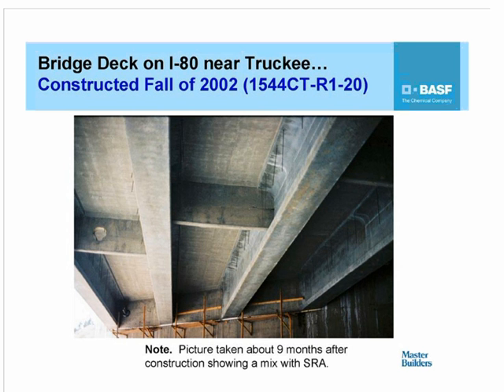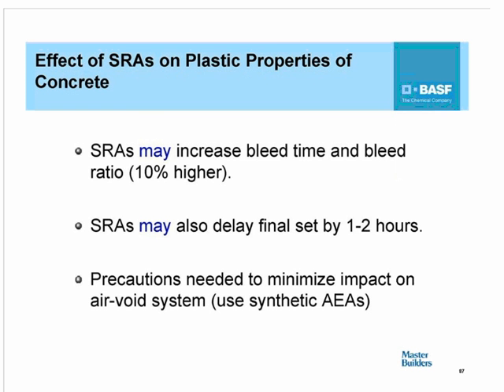The companion bridge deck with the shrinkage reducing admixtures exhibited no cracking whatsoever. Now, these materials, as I indicated earlier, may affect the plastic properties of concrete, and these include potentially increasing the bleed time as well as the bleed ratio, and then also, depending on the ambient conditions, they could delay the time of set of the concrete, especially when used at the very, very high dosage levels.